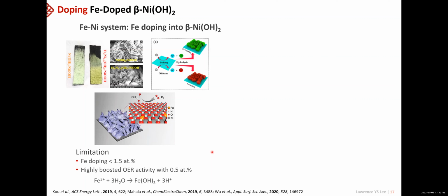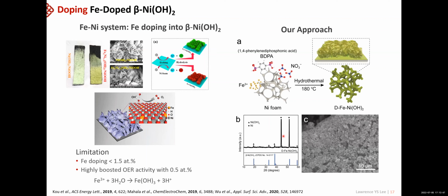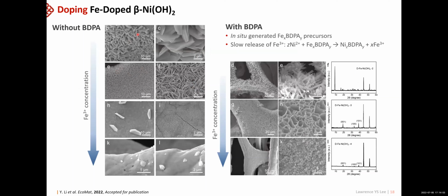So with this idea, we tried to maximize the iron doping into the nickel by using 1,4-phenylene diphosphonic acid (BDPA) as a kind of precursor species. We also tried to dope iron into the nickel hydroxide species without using the BDPA. As you can see, as you increase the iron species concentration from 0 to 0.1, which is less than 1 millimole, in this condition, when you use only 0.1, you can grow nice nano-array structures. But as soon as you increase further, you don't form these nice structures; they become a chunk of big particles, and most of the surfaces are bare. So they fail to grow or stick to the surface.